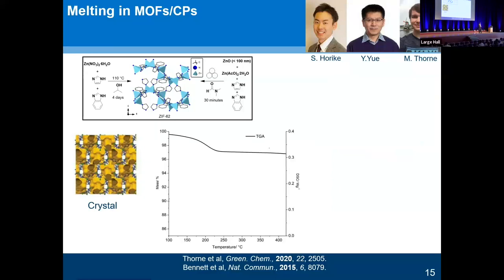So we took a TGA. And we took a TGA, that's brilliant, it's a constant rate experiment. And we looked and said, well, that's solvent loss. Here's a beautiful plateau. That means the molecules, the MOF, sorry, is stable to 450 degrees. Yeah, great job, let's go home. No, no team, it's not. It's actually, this is a rubbish experiment for a number of reasons.